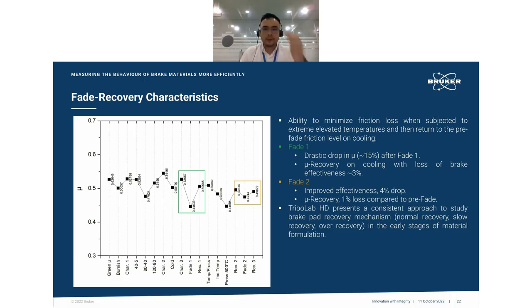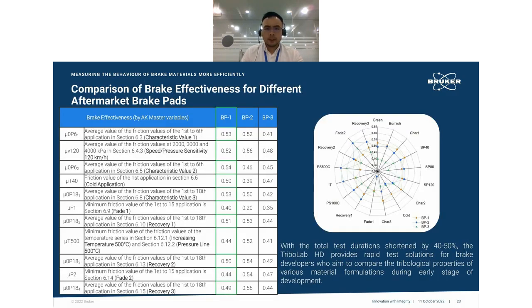So the TriboLab HD actually presents a consistent approach for brake developers and researchers to study the brake pad recovery mechanism, whether the brake pad would recover normally, there's slow recovery, or it may even happen in certain cases, over recovery, where the friction coefficient in the recovery phase is higher than that of the pre-fade step. So this will give good insights in the early stages of material formulation and help to improve on brake formulation. And we had the opportunity as well to compare the brake effectiveness of various market brake pads.